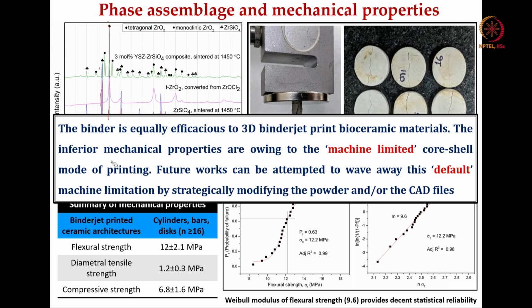So, the message mentioned in the center of this slide is this: the total binder formulation, where you mix the initiator with the powder and then use the monomer solution together with the accelerator dissolved in deionized water, allows in situ polymerization to take place during the binder jet 3D printing. This approach was also efficient in 3D binder jet printing of bioceramic materials. However, mechanical properties remain inferior, and that is due to the machine limited core shell kind of printing.